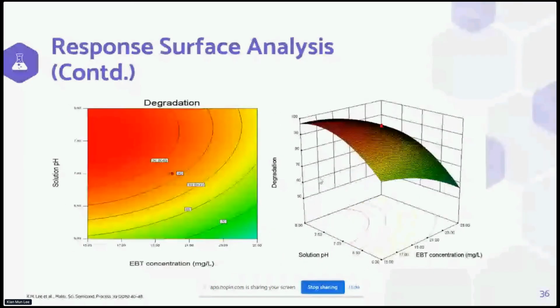Next, I want to share with you the interactive effects between the concentration and the pH. We can see from here that the degradation efficiency reduces with increasing concentration. As I mentioned earlier, this is due to the photons being intercepted before they can reach the catalyst surface. So if photons cannot reach, the active sites on the catalyst surface will be inactivated, which reduces the PCO rate of the dye. Another possible reason is the Coulombic repulsion between the negatively charged catalyst surface and the hydroxyl anions at highly alkaline conditions, which also reduces the removal rate by suppressing the generation of hydroxyl radicals.